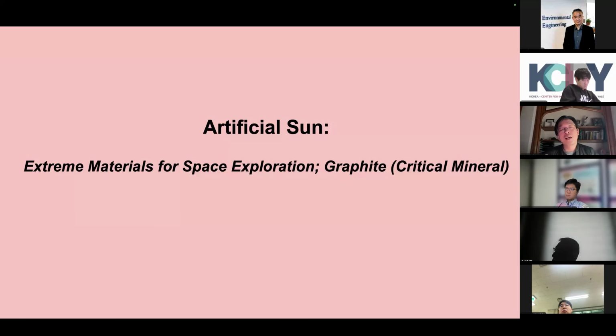In this case, we are pushing the temperature to an even higher value, higher than the surface of the sun. The surface of the sun is about 6,000 degrees C. Okay, here I'm talking about 8,000 degrees C. So why do we need that, right? Using this extreme temperature, 8,000 degrees C, you can pretty much break any bond in any materials, like metals, chemicals, and nitrogen gas, carbon. All these bonds are very weak at this temperature.